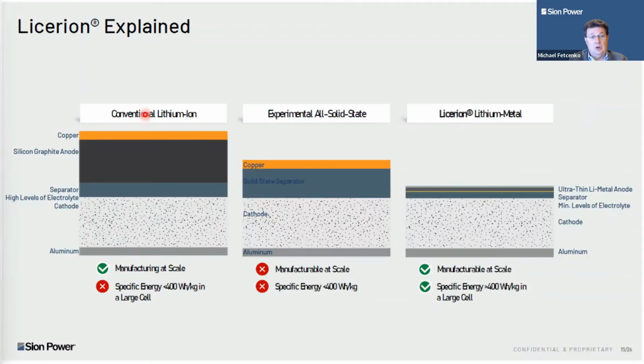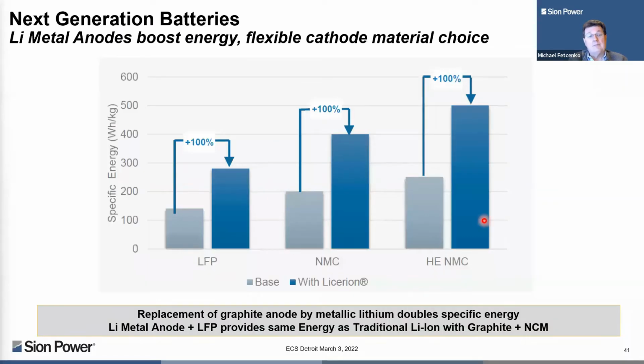So let me do a comparison then of lithium ion, solid state with a thicker separator that's actually loaded with lithium, so it's not necessarily a lower amount of lithium in a solid state design, and what we call Licerion. So we're using the same cathode. We're cathode agnostic. You can use LFP if you want, you can use NCA, you can use NCM. We tend to use nickel 811 for almost all the data that I'll show you in a moment. But people want to know, what is Sion working on? It's lithium metal anode with conventional lithium ion cathode, conventional lithium ion separator, and conventional lithium ion electrolyte with a twist. We do change the formulation a little bit. I'm going to explain why in a moment. So here's what I mean.